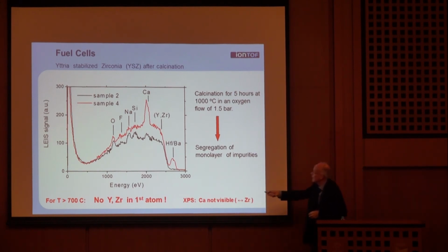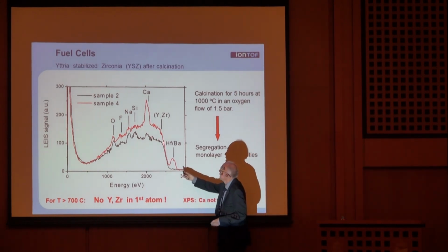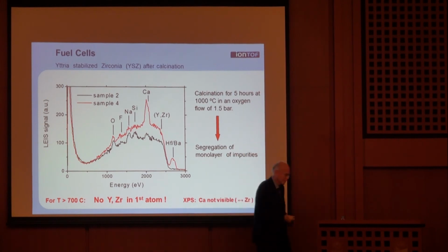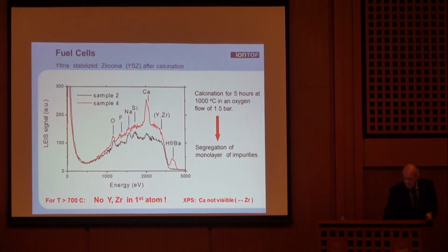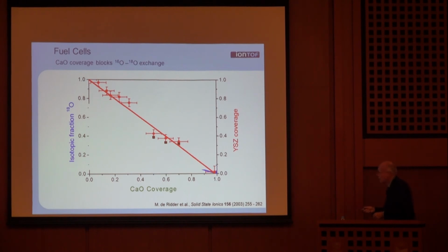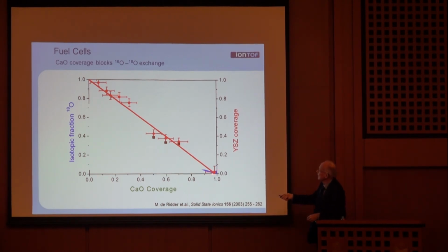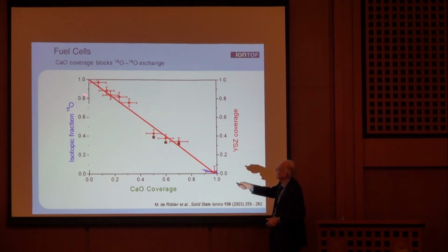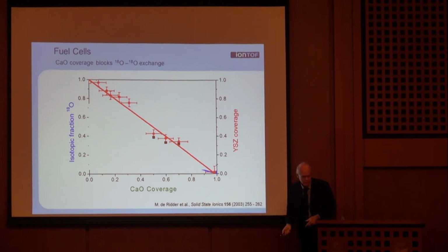And so you see the tail, the background here. Yes, there is a step because there is yttria and zirconia in the second layer, but not at the top. So if I plot, in this case, my signal as a function of the amount of calcium oxide, if I slowly heat up that SOFC, then I see that my coverage of yttria and zirconia goes down and the calcium oxide goes up.